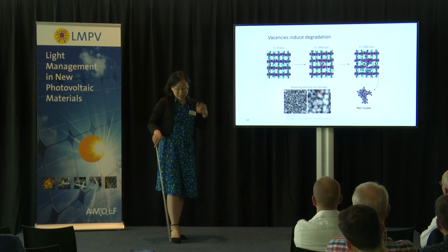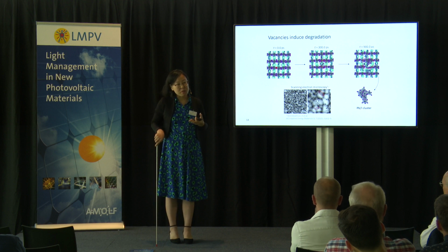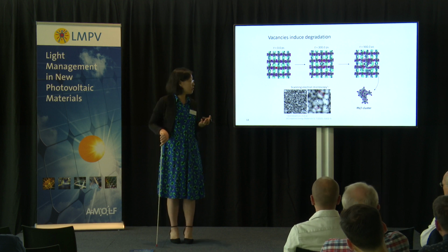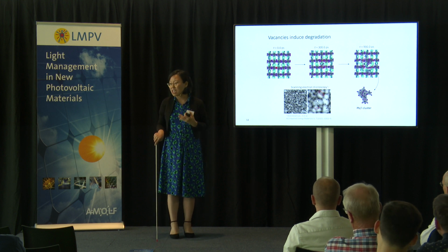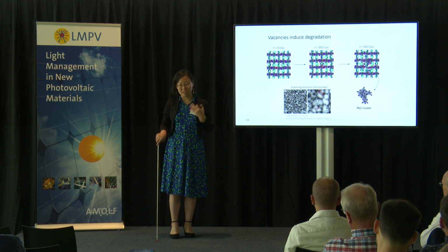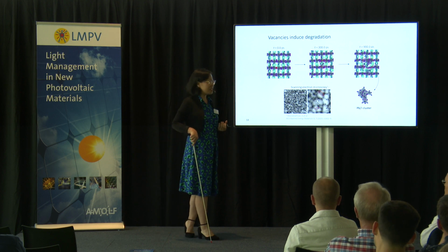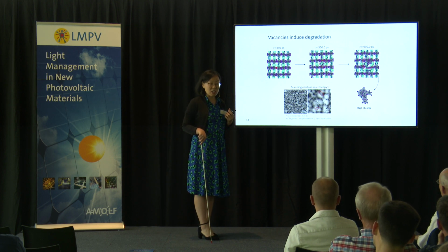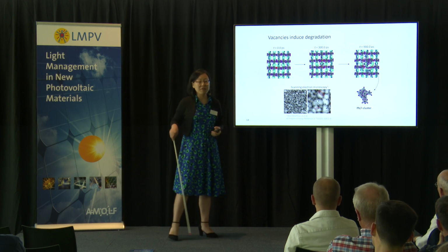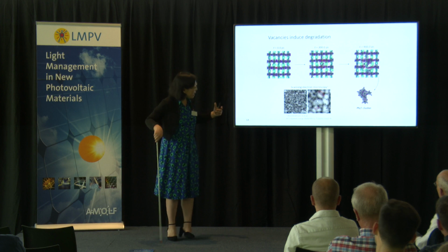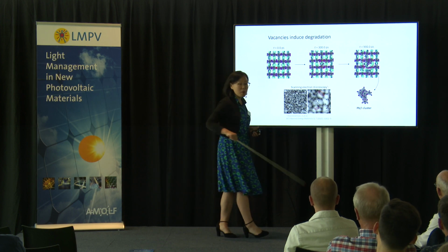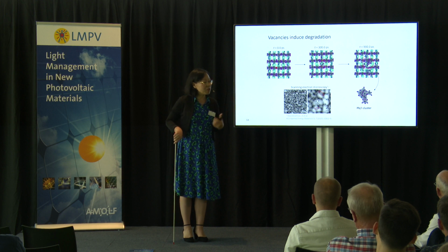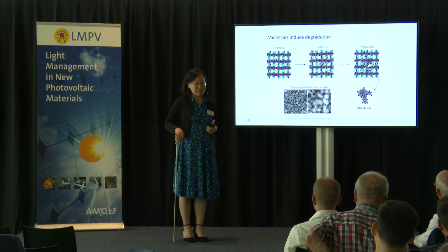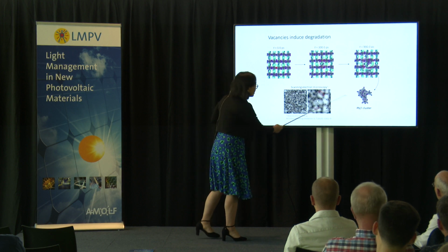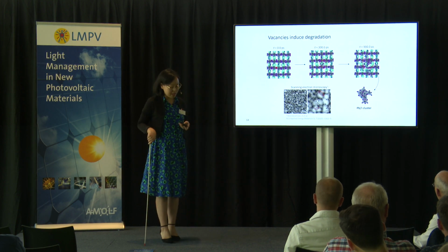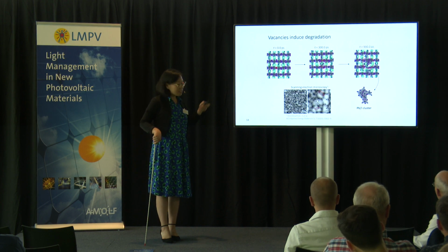So we experimented with these 2 typical defects, again vacancy or interstitial. We find both of the ions are extremely mobile. They travel around in the lattice all the time, at picosecond frequency. Interstitial does not do much, but with vacancy, after a few nanoseconds, we actually get a degradation product like an amorphous lead iodide layer. This layer becomes photoinactive, and you will lose the efficiency of the cells, of course. And these spots actually correspond nicely to the sun image we are showing here. So this is a point defect.